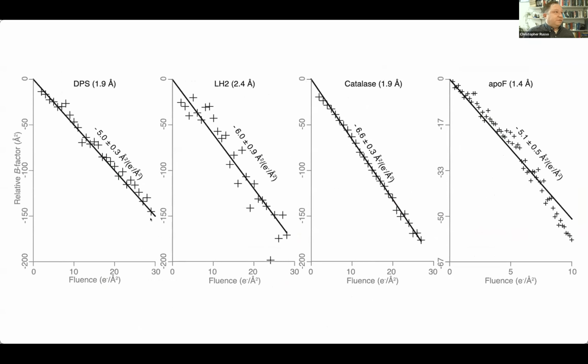We've done this for several molecules now. I'm just showing a few of them here. This is DPS, this is light harvesting complex 2, this is catalase, and this is apoferritin. Some of these have been published and some of them haven't. But in this case, all of them give this linear fit back to 0 dose, which is what we want to see. So again, every single one of these, the first frame is the best, and it is consistent with our notion of radiation damage, which we measure from X-ray crystallography.